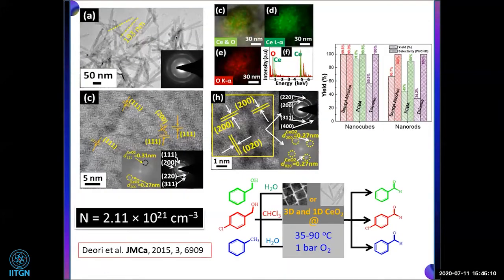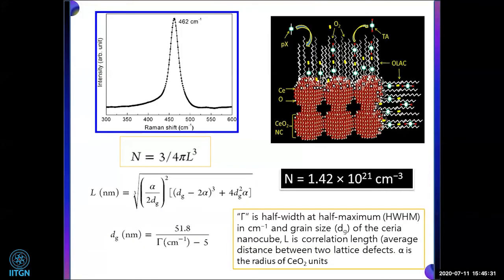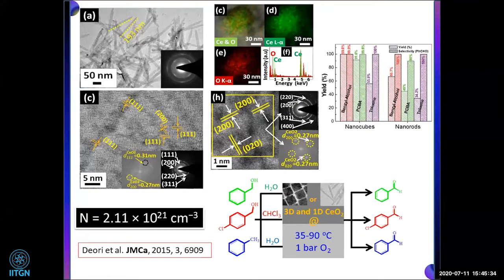And further, we annealed the sample and did more reactions, and then we got the same morphology but with highly exposed 200 facets, as we can see here. So in this case we make cerium oxide nanorods and nanocubes, which is different from the previous one. In this case, it is the oxidation of alcohol to aldehyde. Here we have more defect sites, N is equal to 2.11 times 10 to the 21 per cubic centimeter.